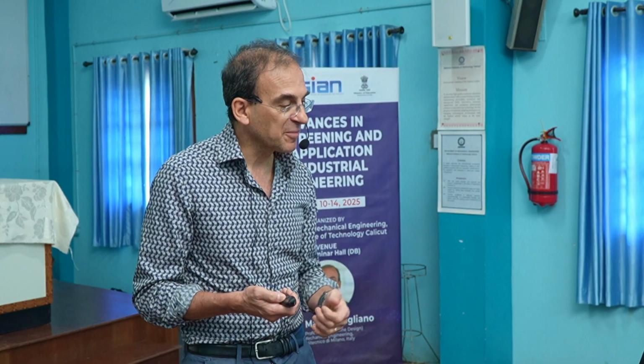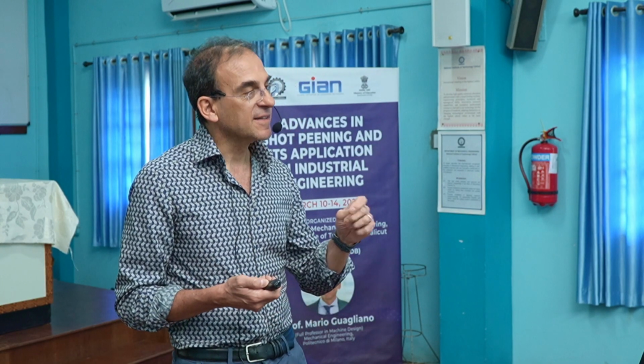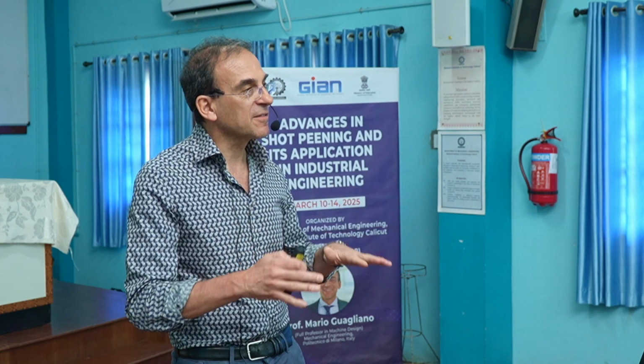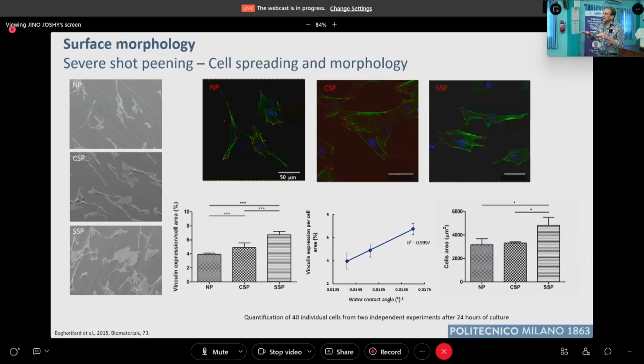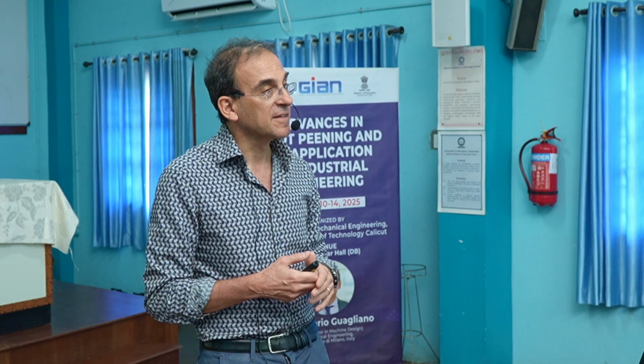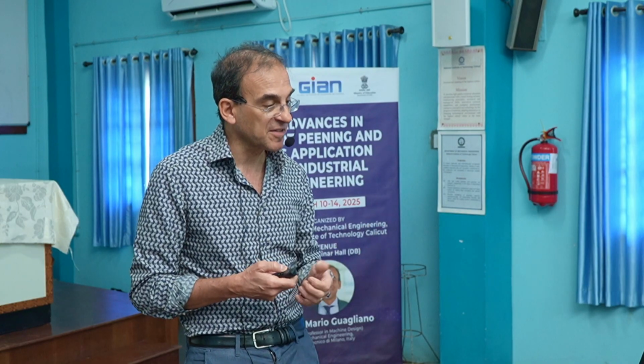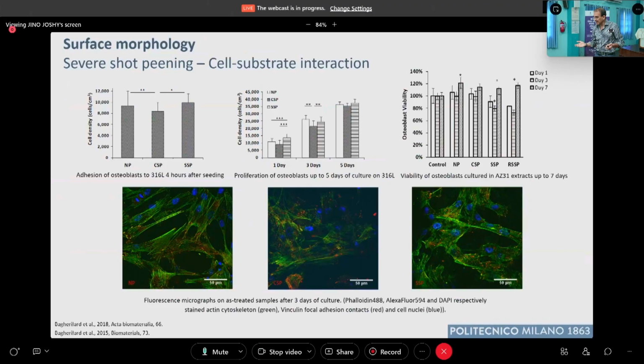That is, for osteoblast viability, what you say is true. But if we consider the spreading of the cells, that is to say, the area of the sample that is occupied by cells, in this case severe shot peening makes sense. We have more area that is covered by the cells. This is an important factor. If we refer to this graph, to the viability, you are right. The graph says that indeed, in the initial stage, the not peened sample is aligned with conventional shot peening. That is to say that severe shot peening is somehow decreasing the viability from this point of view.